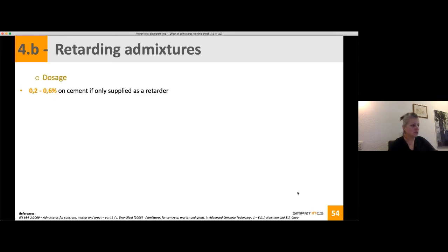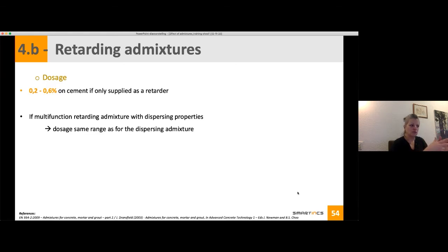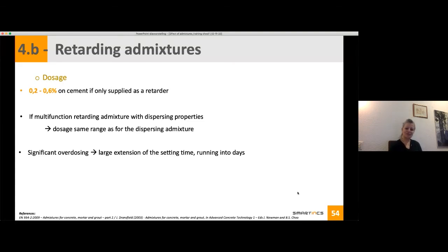Relating to the dosage, it's also a low dosage, 0.2 to 0.6 on a weight of the cement. And if it's a multifunction, so a retarder plus dispersing properties, then the dosage range that is used is the same as the dispersing admixture. You should be careful using retarding admixture. If you have a real overdosage, which also happens sometimes on site, you should take into account that the setting time is really delayed, and then it can run into days. So you have a significant delay on the setting time.